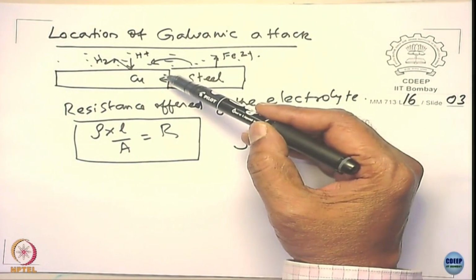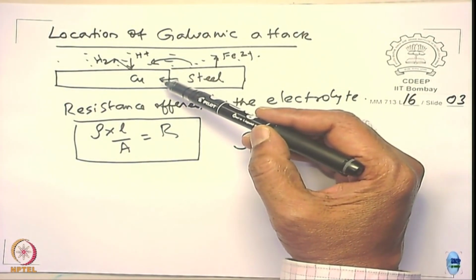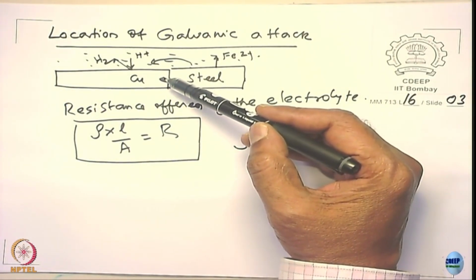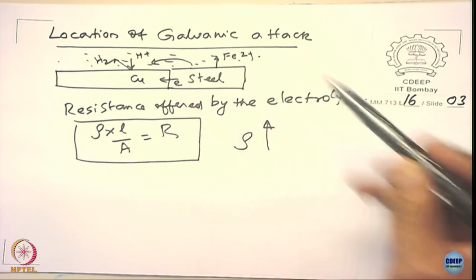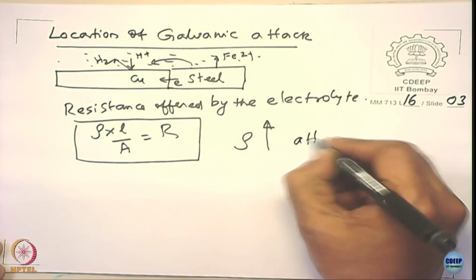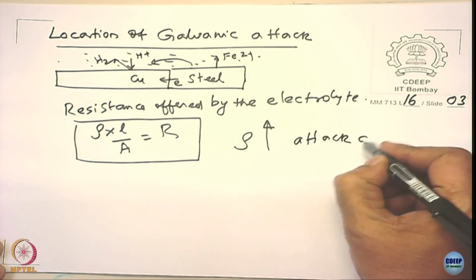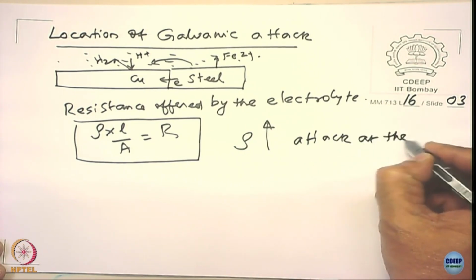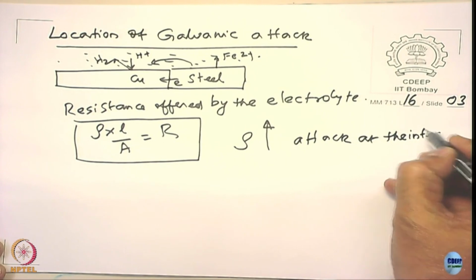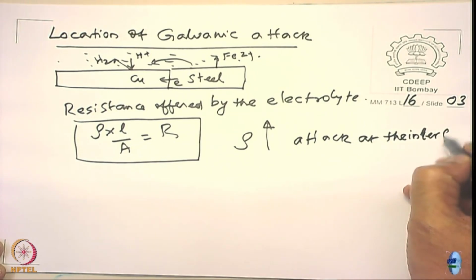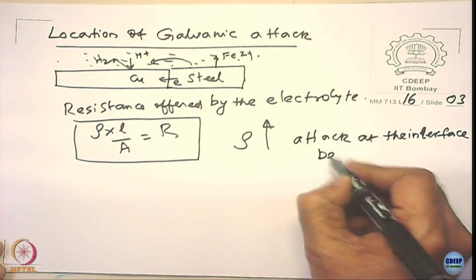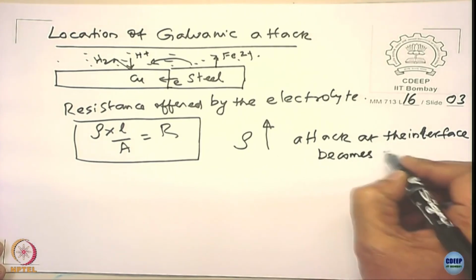That is true, but between the two, the resistance is higher in the electrolyte with higher resistivity. So when the resistivity is more, the localized attack is more, and the attack is confined to the interface, more than the attack away from the interface.